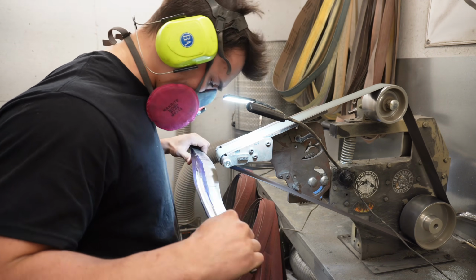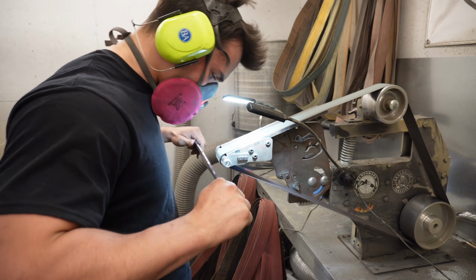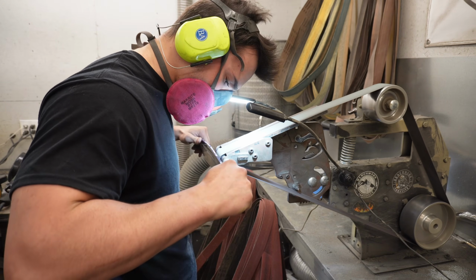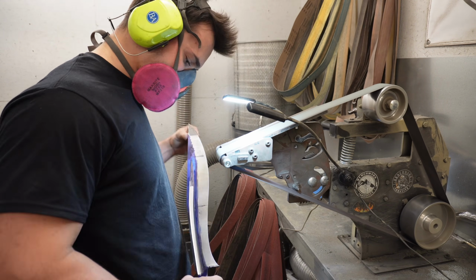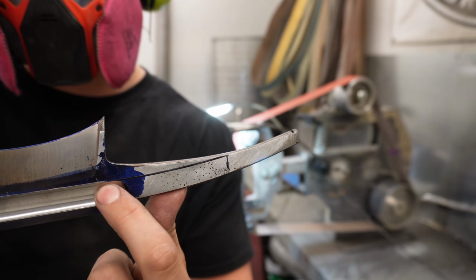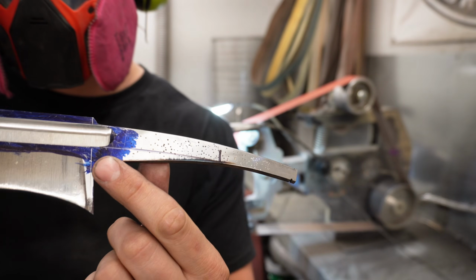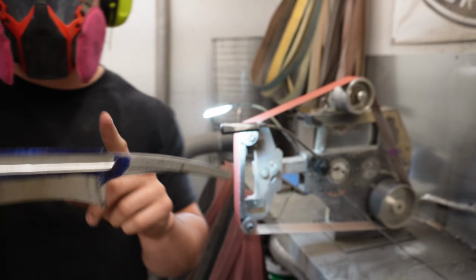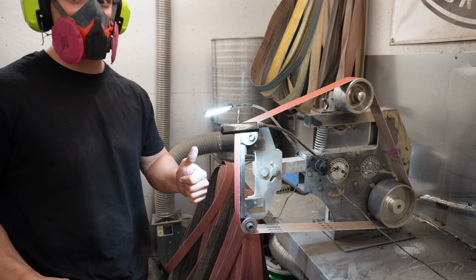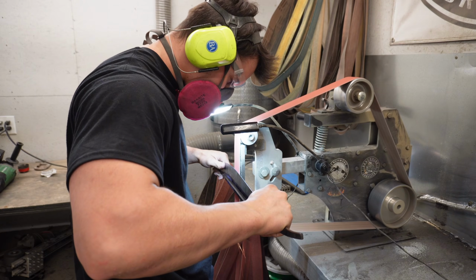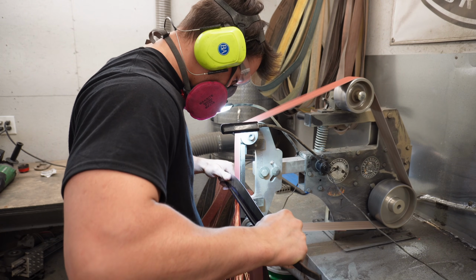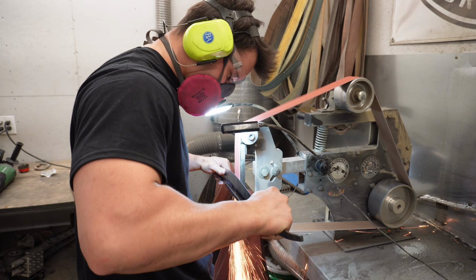I won't lie, grinding that fuller was a little bit challenging simply because it curves, it flares, it doesn't have a constant depth, and it ends in points, so they had to be perfectly lined up on both sides and at the exact same level. Now that the fuller is finished ground, as you can see, I'm going to be pulling that bevel back into the tang, and so I can actually fit the guard all the way up on the tapered blade and have it be a seamless fit.